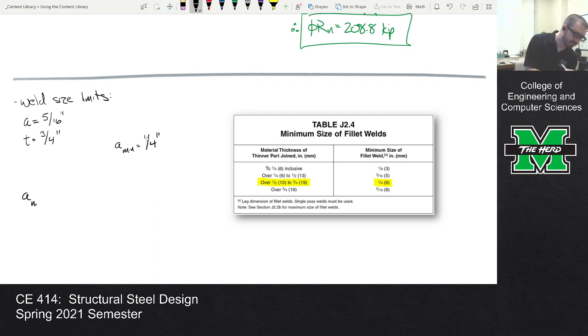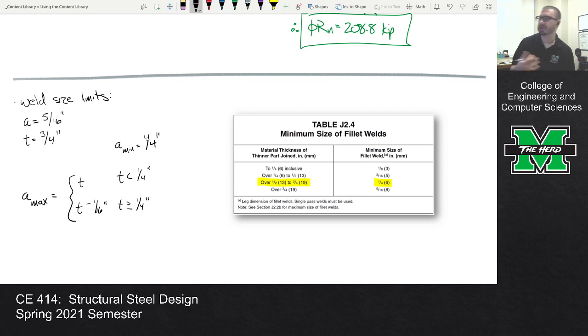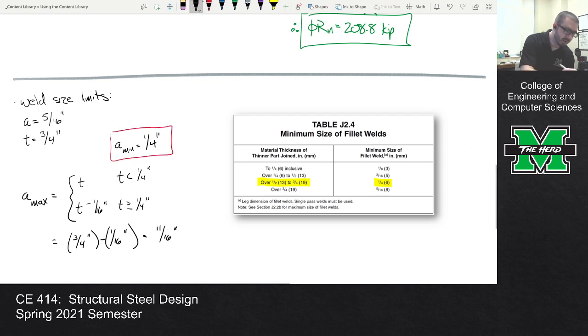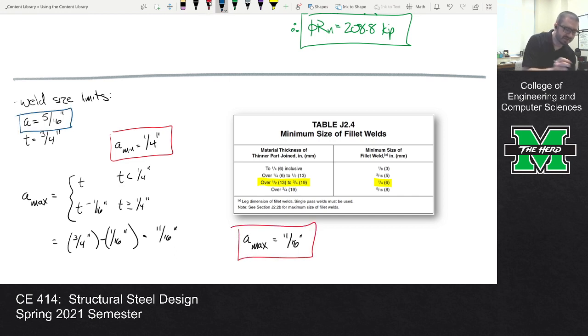As for a maximum, it is either the thickness or the thickness minus 1/16 of an inch, depending on whether the thickness is less than 1/4 of an inch or greater than or equal to 1/4 of an inch. So we're clearly on the second row, and so that's going to be 3/4 minus 1/16. 3/4 is 12/16, and 12/16 minus 1/16 is 11/16. So we have a min of 1/4 and a max of 11/16, and then our weld size is 5/16.